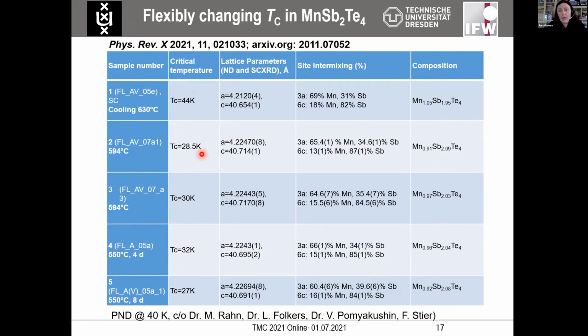One could maybe argue that with increasing temperature, we have slightly less manganese on the outer position, but it could be a counter-propagating trend. However, it seems to not agree well with what was reported by the Oak Ridge group, where they observe, by their synthetic method different from ours, that the overall manganese content in both positions is increasing with the synthetic temperature.